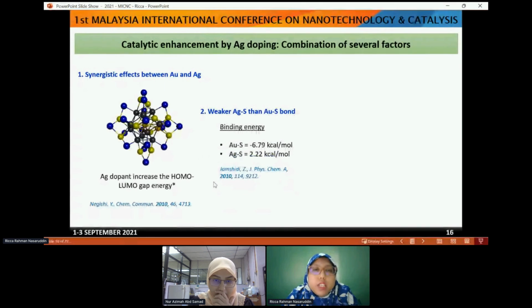And the second reason is because of the weaker silver-sulfur bonding as compared to the gold-sulfur bond. So when we replace the gold with silver, we have weaker bonding between the silver and the ligand. Imagine the reaction: when we remove the ligand, we open the active sites more to the reactants. That is why the catalytic activity increases.